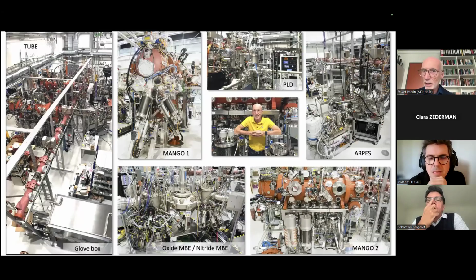So I just wanted to mention, and I showed you this drone video, in fact, if you look more closely, what you would see in this, what we built in the last 6 or 7 years, is a series of thin film deposition systems with which we can grow magnetic, non-magnetic, and superconducting layers. We have on the one hand some molecular beam epitaxy systems, and we also have this system we called Mango, which is a homemade system for magnetron and ion beam sputtering, which are techniques which allow you to explore a wide variety of materials. And we have 2 of these systems. Each system can contain up to 44 distinct sources of magnetron ion beam sputtering, and also we could exchange the subchambers to allow for evaporation, essentially molecular beam epitaxy, all in the same system.